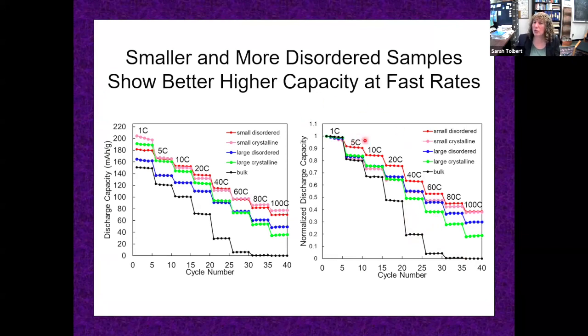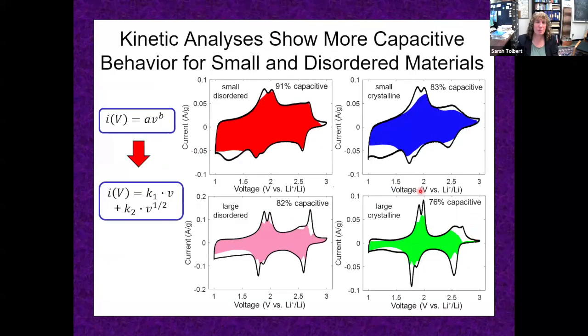The fastest one, the one that keeps the highest capacity as we go fast, is the one that is both small and disordered. And then interestingly, the small and crystalline and the large and disordered are almost identical. And so what this says is that disorder and size can both equivalently be used to make materials charge faster.